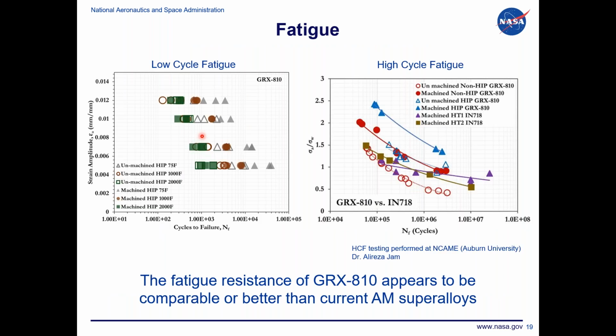We've also done fatigue properties, both low cycle fatigue and high cycle fatigue. I'm not a fatigue person, per se, so I'm less confident when I'm presenting this data, but I think the most important takeaway is that we haven't compromised our fatigue properties to get these great creep properties. In superalloys in the past, what you usually give up for better creep is worse fatigue. But because we're getting this great creep performance from this special composition and the nano oxides, we actually haven't given up any of our fatigue properties.